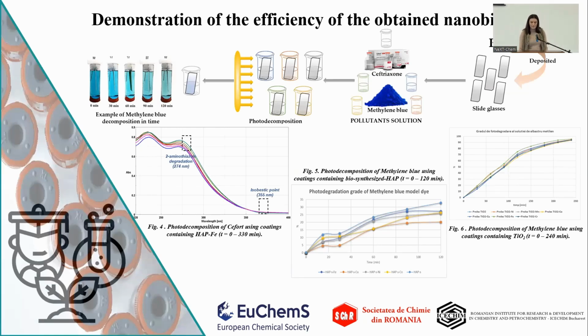So the next step was to demonstrate the efficiency of the obtained materials. We chose for this objective 2 important pollutants that we usually find in the environment. One of them is a model contaminant, methylene blue, and the second one is a commonly used drug, ceftriaxone. For this study, we mixed our photocatalysts with a styrene acrylic paint and deposited it on glass slides, and the glass slides underwent the photodecomposition process in a photocatalytic reactor under visible light. We obtained the photodecomposition of ceftriaxone using the coatings containing hydroxyapatite with iron.